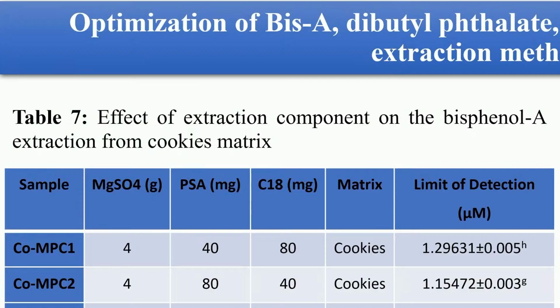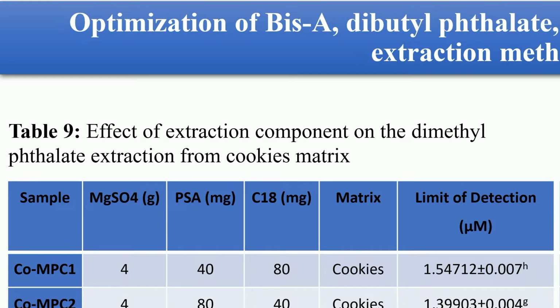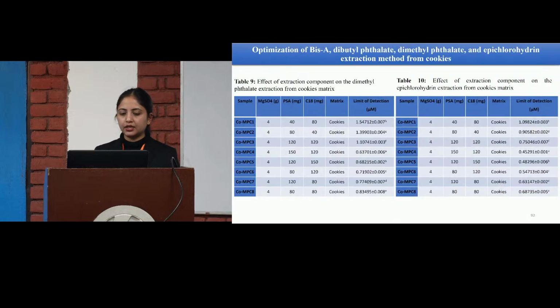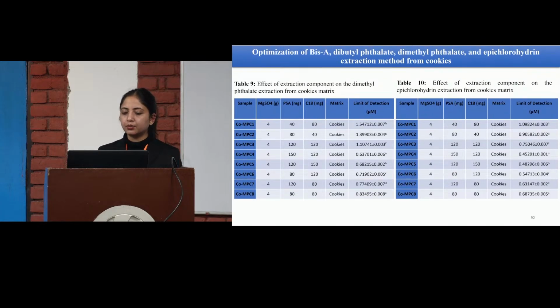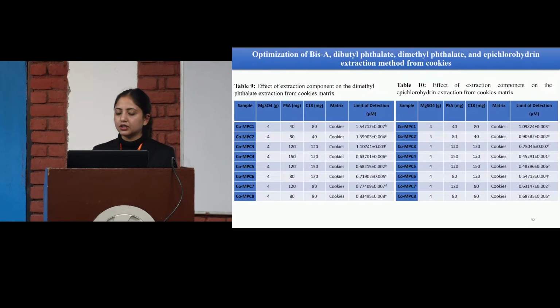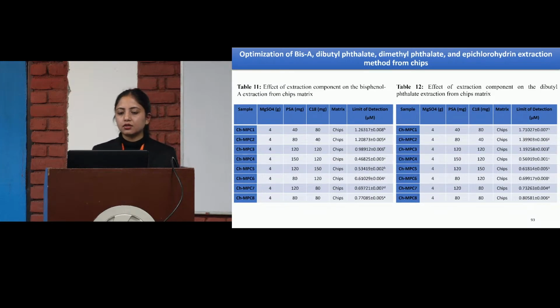Then for the dimethyl phthalate extraction from the cookies, we also used PSA at 150 mg and C18 at 120 mg. We optimized the extraction of the dimethyl phthalates from the cookie sample, and 150 mg of the PSA and 120 mg of the C18 got the best, least limit of detection, that is 0.63. And in the case of the epichlorohydrin, we used 150 and 120 of PSA and C18 for the least limit of detection.